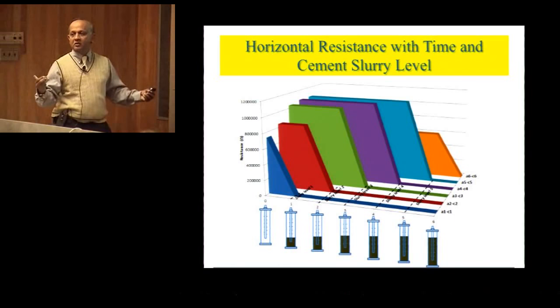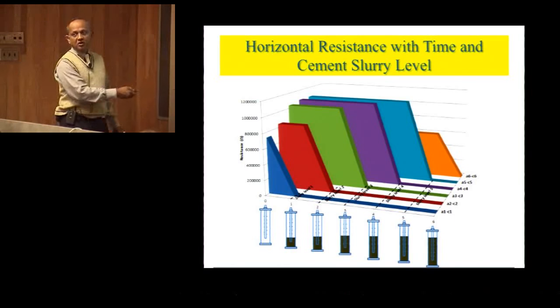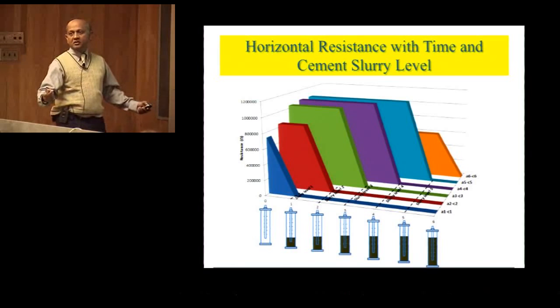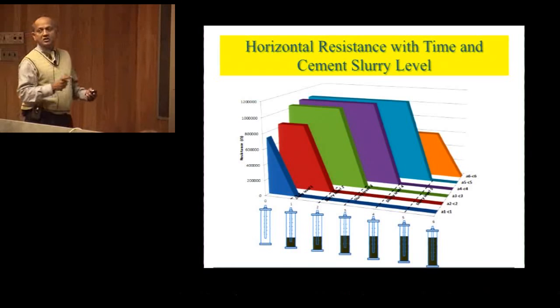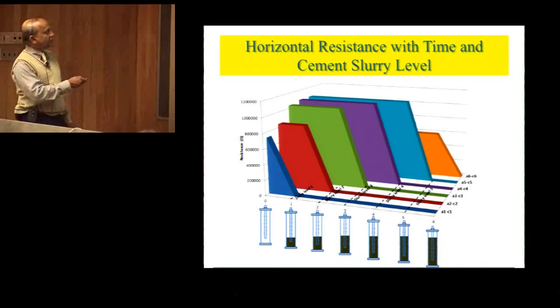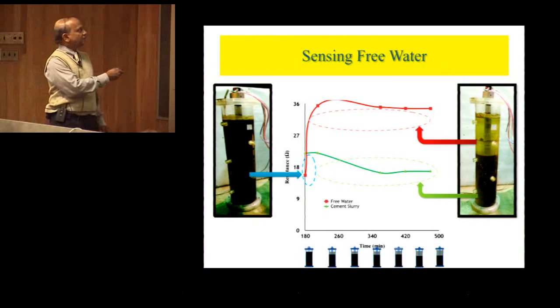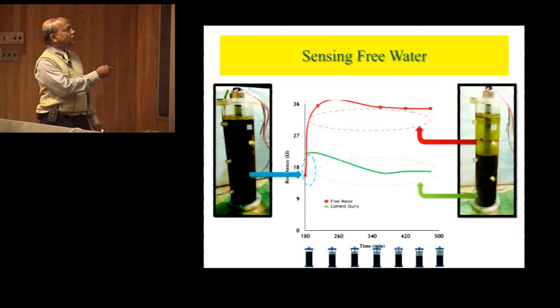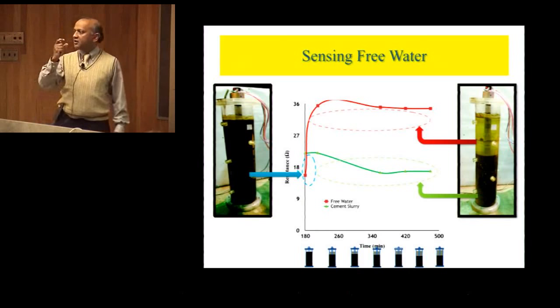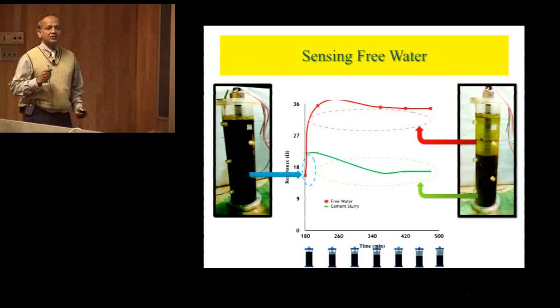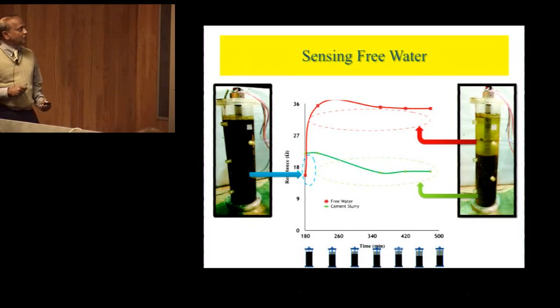These are not small numbers. These are huge changes, so you really know the change has happened. Then moving on, these are lab model tests that we are doing. Here is another interesting one where we had a very high water to cement ratio. We just put it in there. This was the resistivity we measured. Within hours, bleeding occurred, and the resistivity on the top more than doubled. So you can really say something is going on in the cement and modify it.